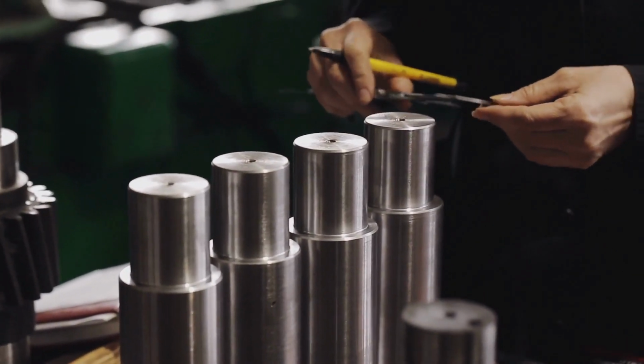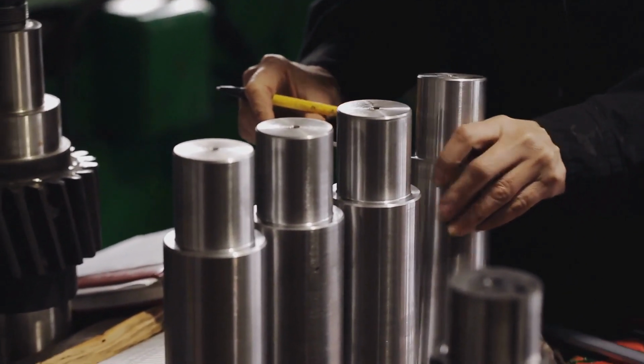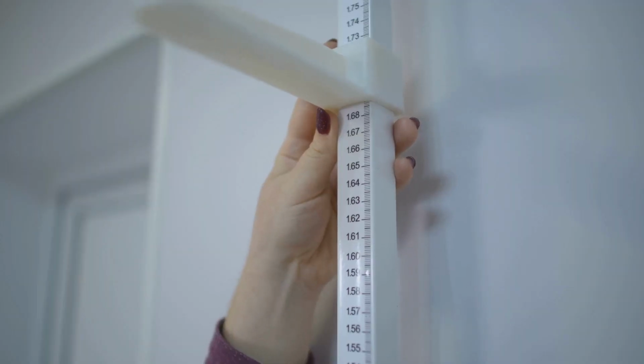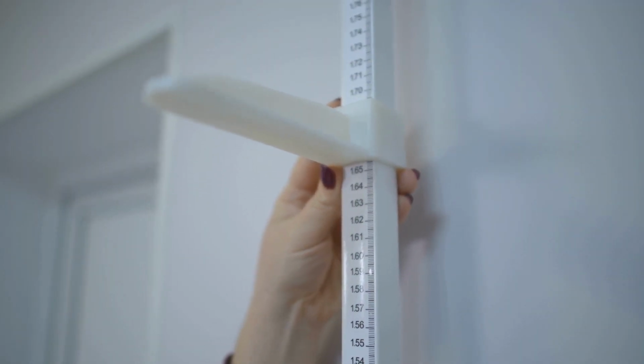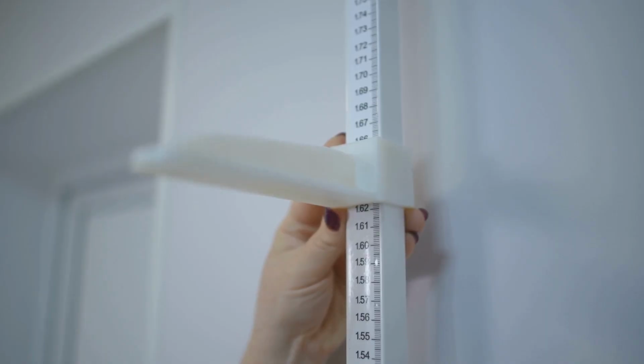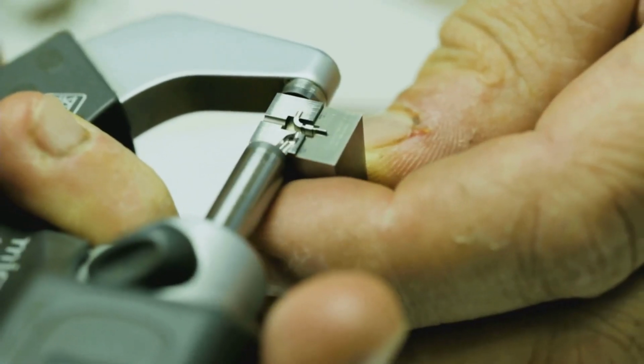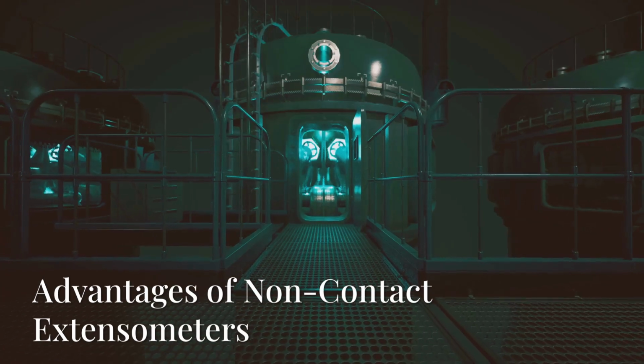Specimens that require the use of contact extensometers are first marked with measuring marks, which are either clipped, tacked, or glued onto the specimen surface. These measurement marks can become indistinct, fall off, or deform under load and are therefore a significant source of error.